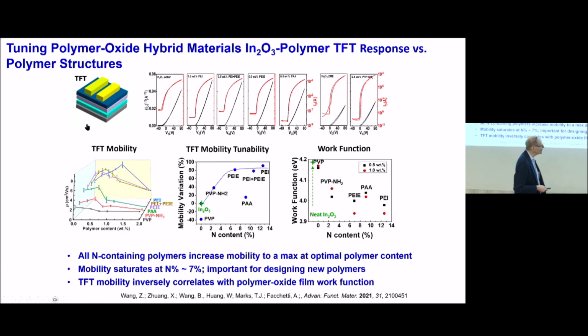So you might say, yeah, you got lucky. You tried one oxide and it worked. You tried one polymer and it worked. And so this is just showing you a whole group of polymers. We've made transistors of them. And basically, the mobility scales as the work function. So the more and more electron-rich the polymer is, the more and more it fills the traps, and you get, here's the nitrogen content and the mobility, and the work function and the mobility. So it's reasonably linear.